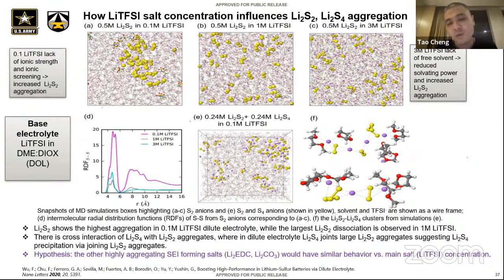As you show here, when you develop the force field for Li2S2 or Li2S4, do you have any covalent interactions between the lithium and sulfur, or just cation-anion? I don't. And there is an interesting point. It's a polarizable force field. If you do charge analysis, RESP or something like that, on Li2S2 and Li2S4, you will see a lithium charge of about 0.7, 0.6, very low. But if I take the same grid and look at the effect of lithium when it polarizes sulfur, it induces so much electric field towards it that